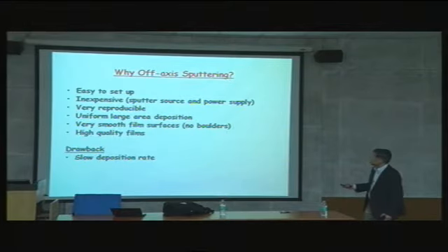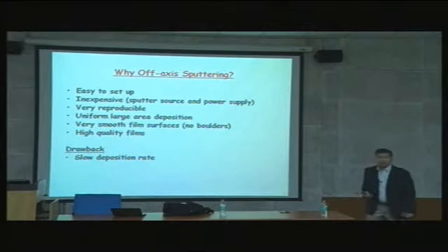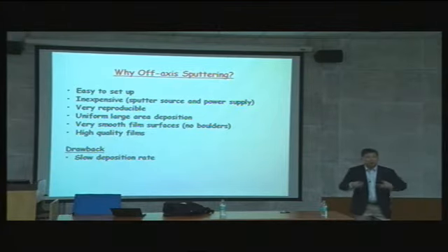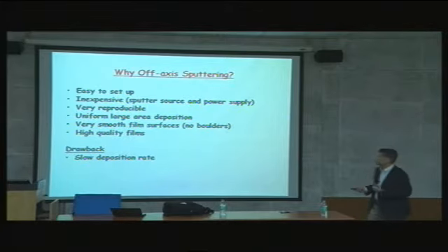The other thing is that the film quality is very smooth, and initially we got better films by sputtering than PLD. PLD creates a lot of boulders and particles, because of the energetic photons, not only creating atoms but also chunks of material coming from the target, especially if the target density is not good enough. I think you have some experience with certain material systems where you get a lot of particles in PLD, but sputtering is less susceptible to the particle issue.